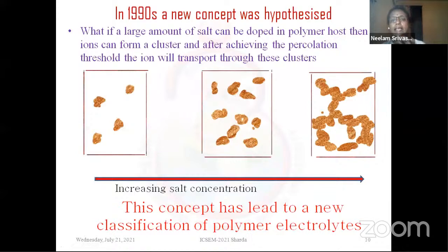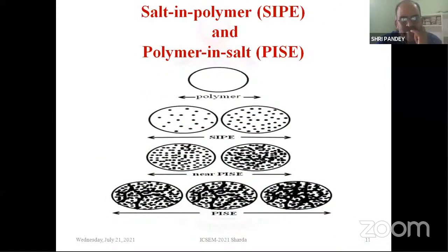In the 1990s, a new concept was given, that if we put a large amount of the salt in these polymers, then there will be a condition when the salt dissociated ions make a cluster throughout the matrix of the system, and then the ion will transport through these ion clusters. And because there will be no segmental motion associated with this transport, the ion transport will be high and very good. And this concept has led to the classification of polymer electrolytes into two categories.